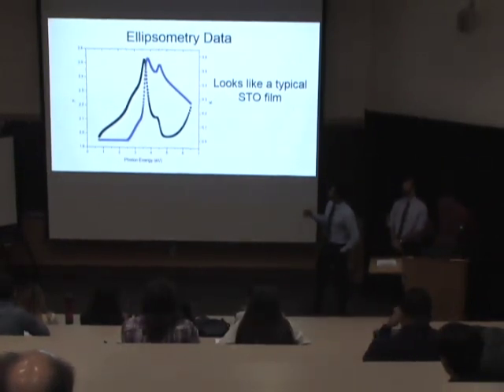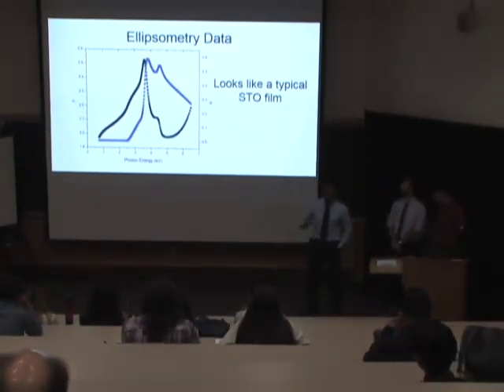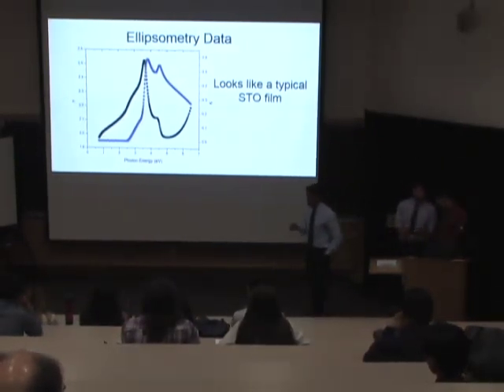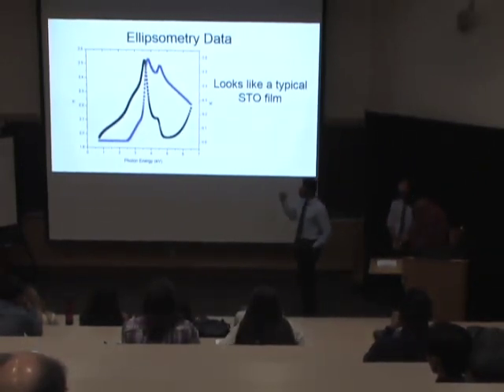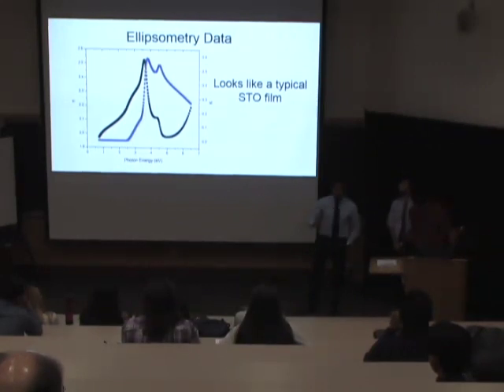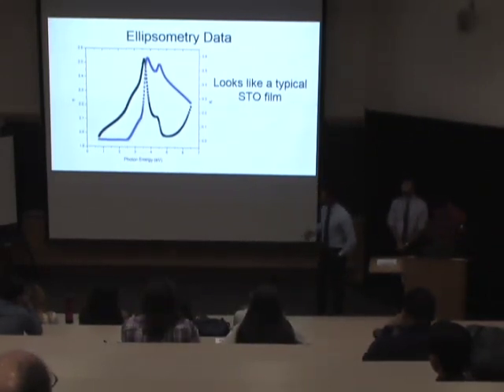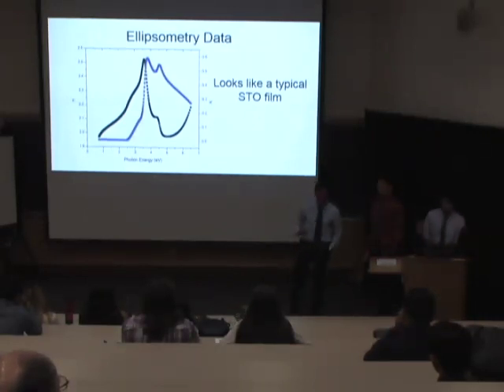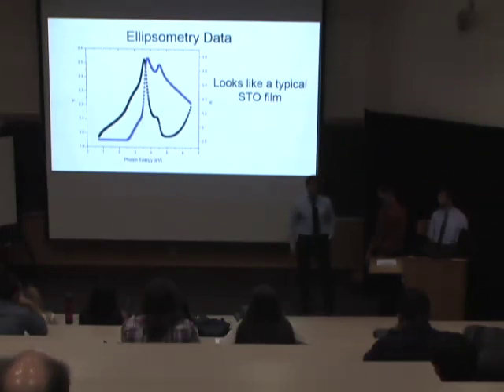Now, this ellipsometry data corresponds to our STO film, which stands for strontium titanate. It tells us two things. As the photon energy increases, the black line represents the index of refraction changes, and the blue line represents the light that's being absorbed. The ellipsometry data is very important because it can tell us anything that's wrong with our thin film, but in this case, our STO film looks perfectly fine. That's the way it should look.